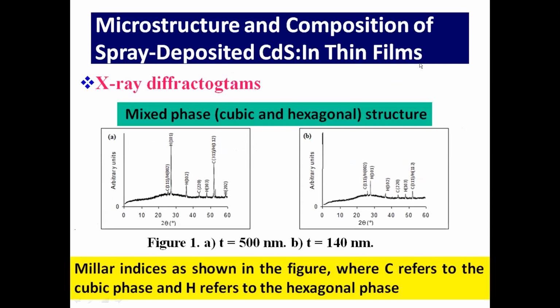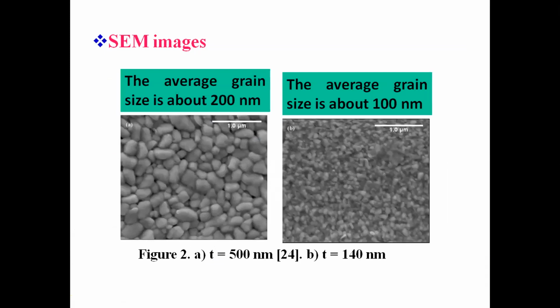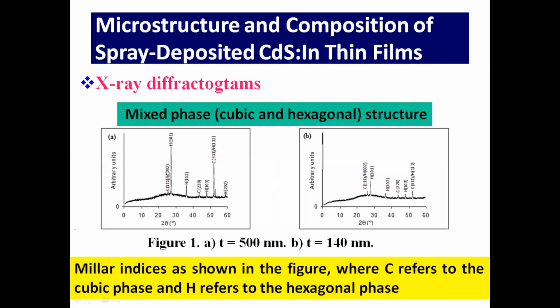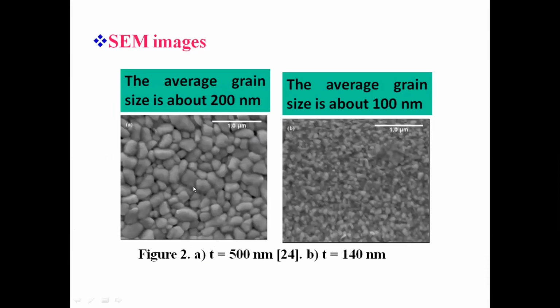First, the microstructure and compositional studies of the spray deposited CdS thin films. Here are two diffractograms for two films, one of thickness 500 nanometer and the other of thickness 140 nanometer. As you see in the diffractograms, the films appear polycrystalline, and they show mixed phase, cubic and hexagonal. Now the symbol C refers to cubic, and H refers to hexagonal. Now in this figure you see SEM images for the same two films. This one is for the thicker film, and the average grain size here is about 200 nanometer, and this one is for the thinner film, and the average grain size is about 100 nanometer.